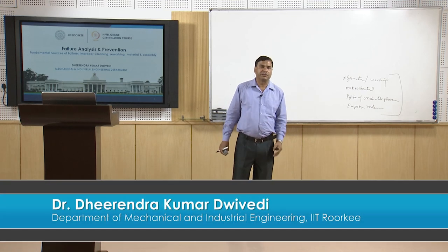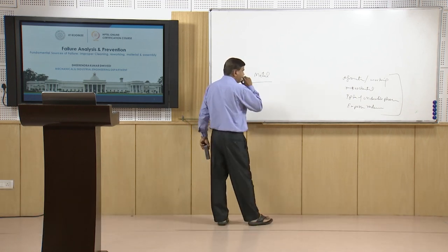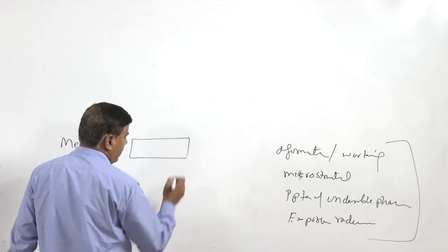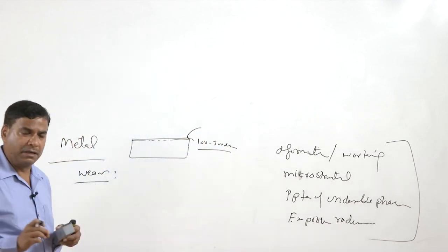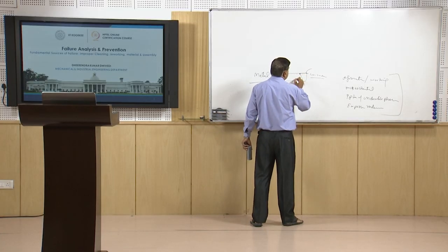Especially for properties for which the resistance of the metal changes as a function of time, selection becomes difficult. For example, here the wear. Whenever wear happens, like abrasive or adhesive or erosive or cavitation, the near surface layers are exposed to the external conditions. In case of, say, adhesive wear, the near surface layers up to say 100 to 200 micrometer depth are conditioned in terms of chemical composition and deformation, so the properties are found to be different at the surface and in the core region.